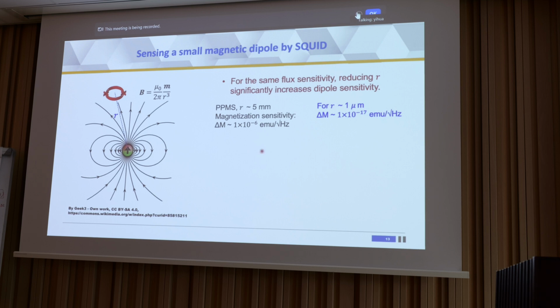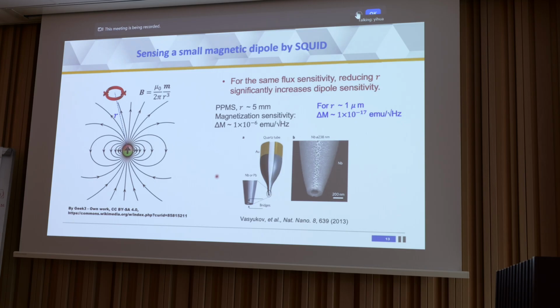So this really demonstrates that if you want to achieve very high flux or magnetization sensitivity, and also perform some microscopy, you need to be very close to what you are detecting. And this is the method that has been engineered by Professor Zeldov's group. They basically make a SQUID on a fiber tip, and they can bring this tip very close to the sample, so that they can achieve very high flux sensitivity as well as perform very high spatial resolution magnetic imaging.